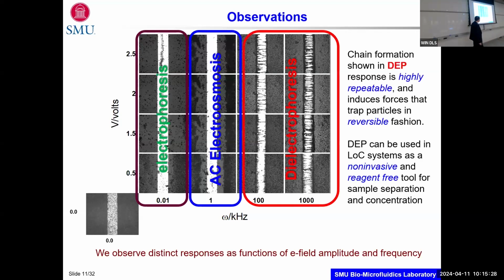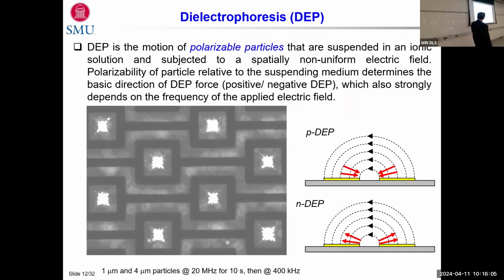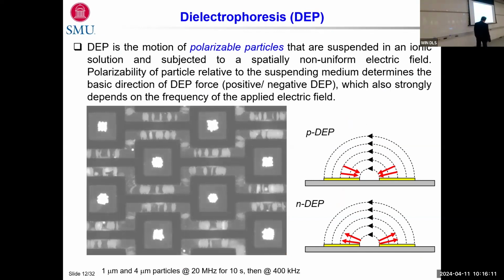But I'm more interested in this chain formation, and that is actually in response to dielectrophoresis, and it creates highly repeatable structures. The forces that it induces are basically reversible. So if I let go of the electric field, I can release those particles, which is good. And it's a non-invasive and reagent-free tool for sample separation and concentration. Let's see how well it works for synthetic particles as well as biological cells, and let's see what the limitations of it are. So dielectrophoresis is the motion of polarizable particles that are suspended in an ionic solution and subjected to a spatially non-uniform electric field.